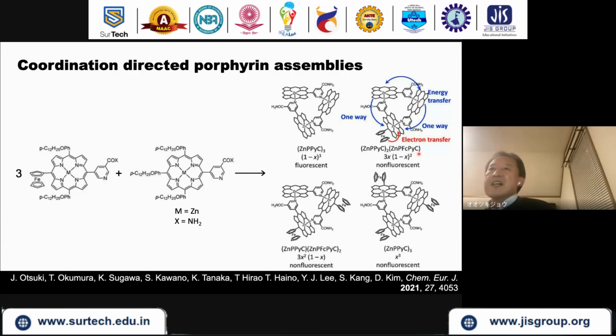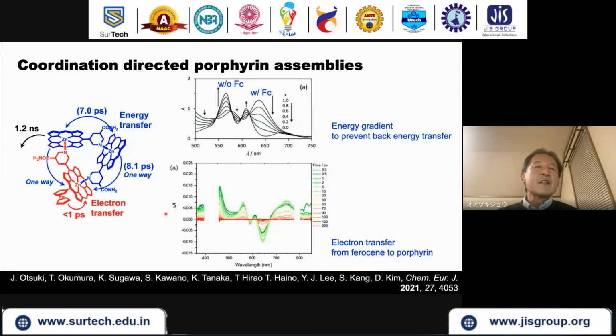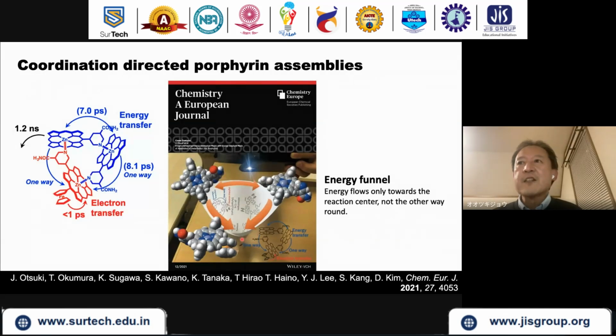This is another type of photosynthesis initial step model. In this case, what is interesting is that by introducing the pyridyl group, the energy level of this porphyrin is lower than the energy level of these two. And so energy transfer happens from here to here, here to here, but not the other way around. So the energy transfer is only one way, which is favorable because electron transfer happens here. And there is no reverse, unfavorable energy transfer involved. So this is confirmed by some spectroscopies. So basically, this is like an energy funnel. Energy flows only towards the reaction center, but not the other way around.